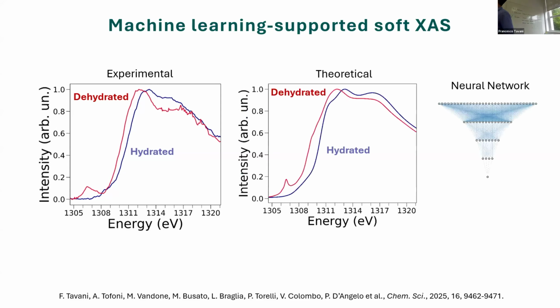And at this point, it's time to compare the experiment with the theory. So actually, the experimental data is quite similar to the theoretical data. So here I'm plotting the experimental magnesium K edge of the hydrated MOF, shown in blue, compared to the experimental K edge spectrum of the dehydrated, or at least partially dehydrated, MOF, shown in red. And you can immediately see that the edge position, again, similarly to the other MOF, so there must be something common between these systems with these water experiments. The edge energy is shifted toward lower energies, and there's an increase of a pre-edge peak.